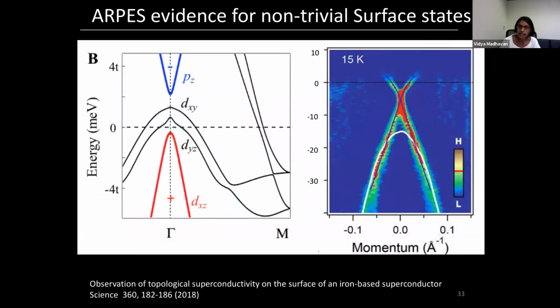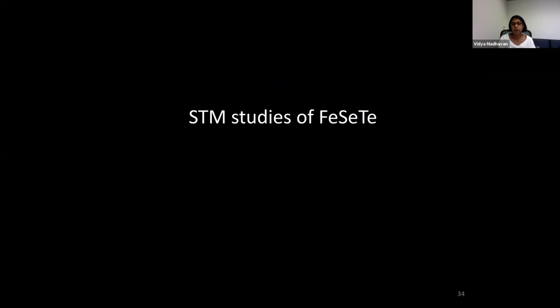So in 2018, a few years after the material was predicted to be topologically non-trivial, they carried out angle resolved photoemission measurements where they could see this directly. So this is energy, this is momentum. You can see there's this band that crosses the Fermi energy. It's got linear dispersion, and they could show that this band was actually a surface state. So this is very promising. This measurement gives you hope that this material might be able to host Majorana modes.